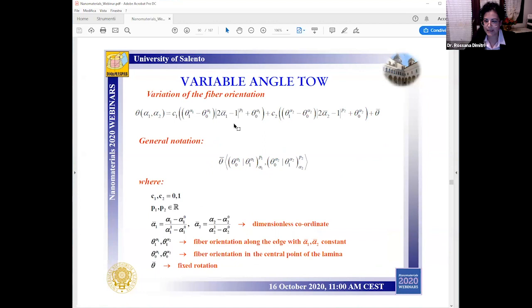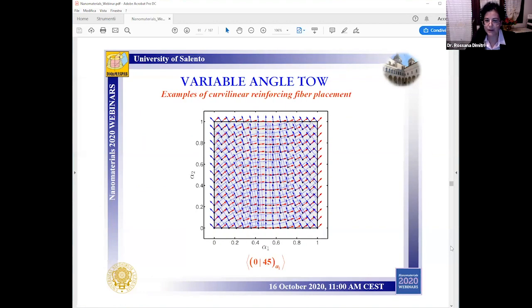So from a mathematical standpoint, the fiber path orientation theta can be written through this law, where you can see theta defined by means of different parameters: the fiber orientation along the edge, with alpha 1 and alpha 2 constant, or the fiber orientation in the central point of the lamina. We are able to consider a variation separately along each coordinate, or a combination of both coordinates and variations. So the desired mechanical properties can be reached by combining these parameters conveniently.